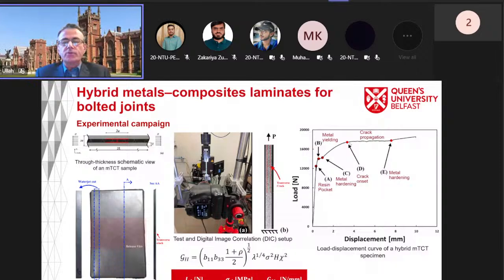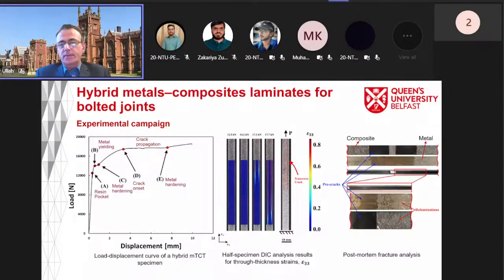And then from here, we calculate the stress. And then we will use this equation here. So if we replace this sigma by this value here, and because we know X, we know all the material and geometry parameters, we will be able to calculate G2, which will be our fracture toughness, which is 1.08 in this particular case. And we also then verify with the DIC that the crack was propagating only in mode 2. And these are some post-mortem fracture analysis. So the proposed test setup allowed the hybrid interface fracture to propagate only in mode 2.